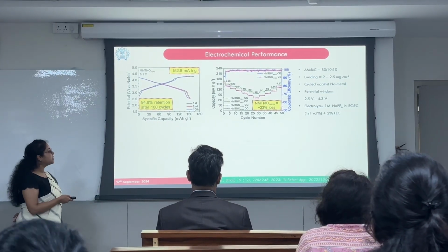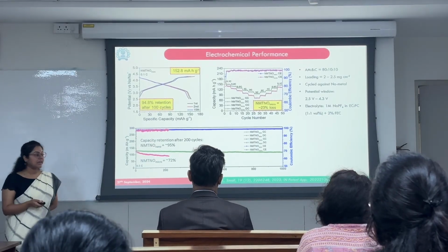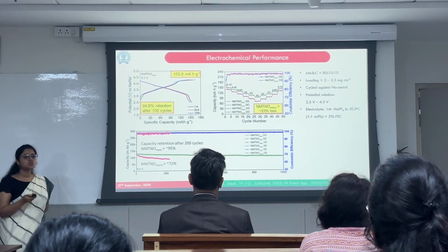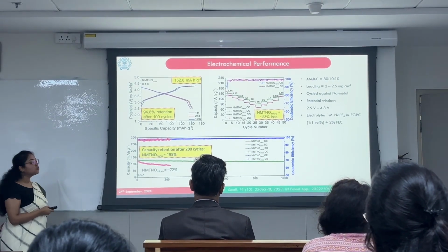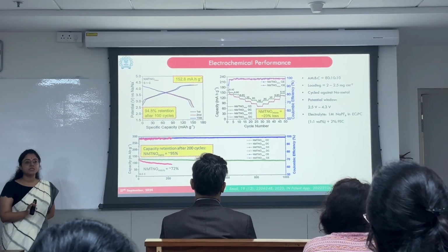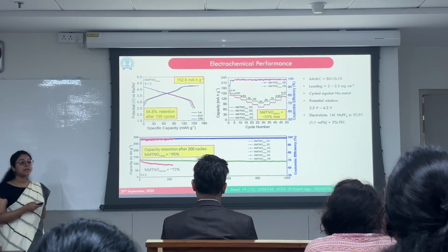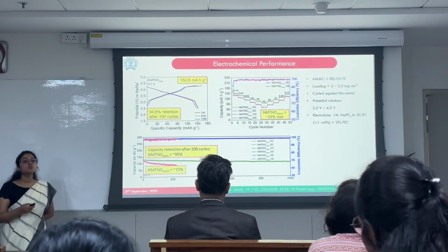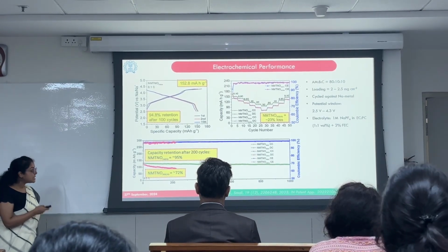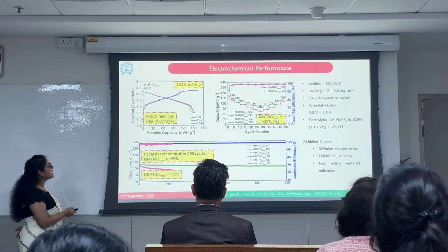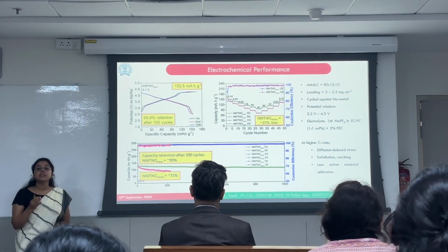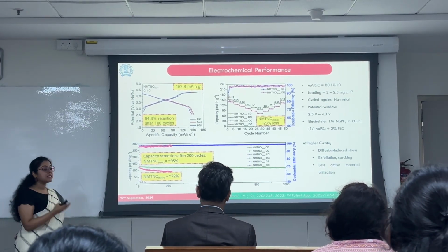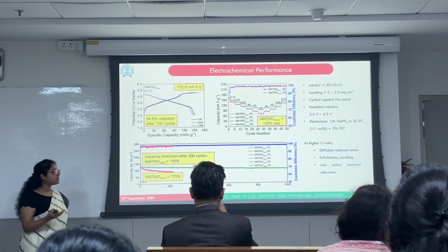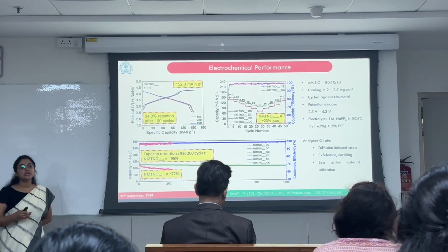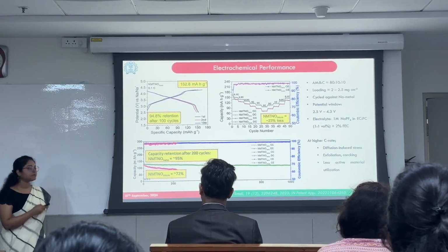So we tested it for long cycle life, and we observed that after 200 cycles, the NMTNO nano gave us a capacity retention of around 95%. However, that of NMTNO micro reduced to only 72%. This could be attributed to the fact that the NMTNO micro suffers from diffusion-induced stress, which leads to exfoliation and cracking, and thereby less utilization of the active material.